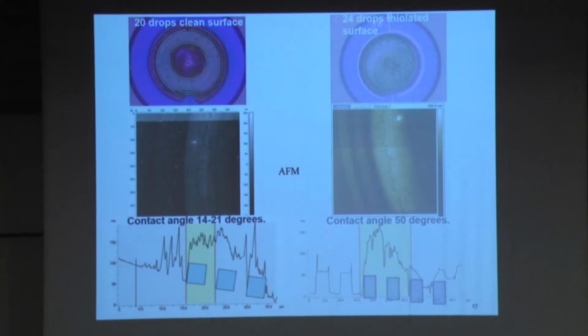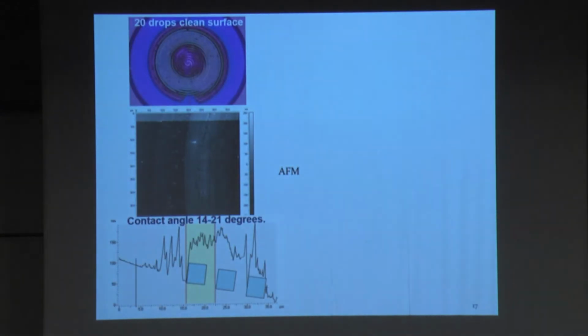A few more slides about jetting. On the left side, we can see wet drops and the dry splats produced by 1 drop, 4, 8, 16, and 20. Well, basically, the physics of this is that the size of the wet splats is controlled only by the volume of the ink and by the contact angle, okay? So by putting more drops, you simply increase the diameter.